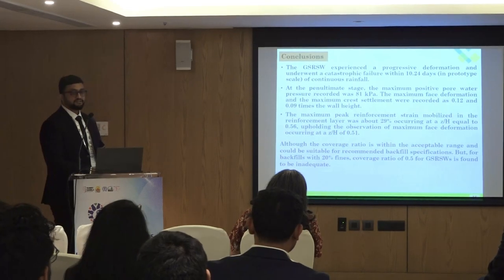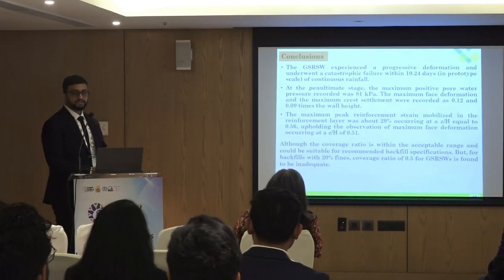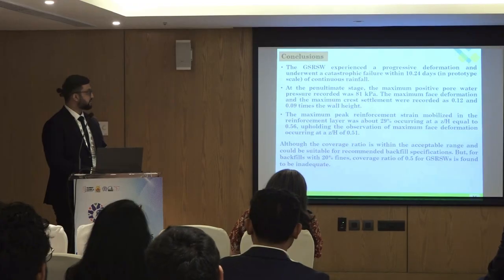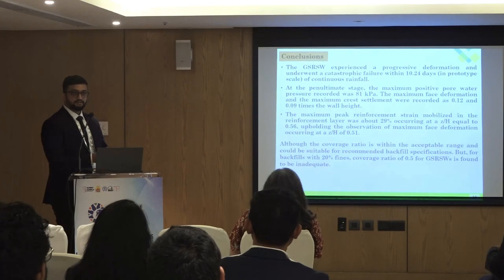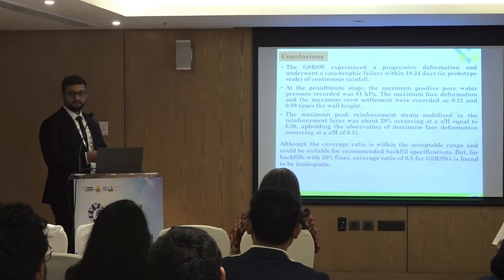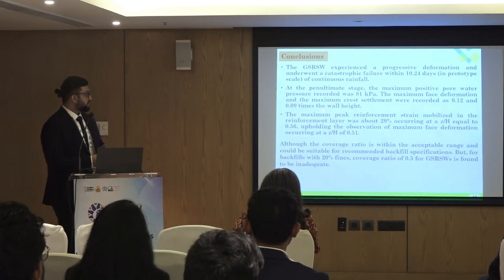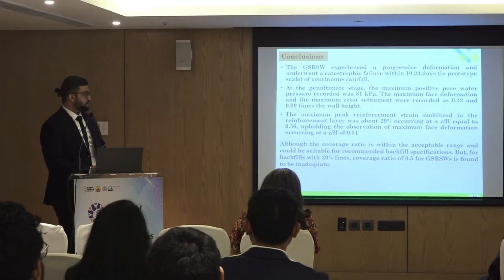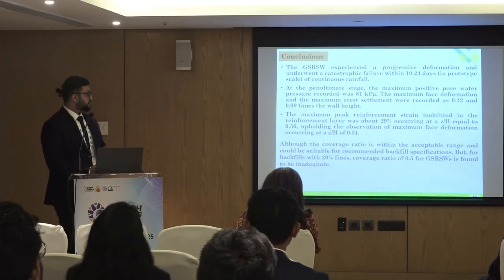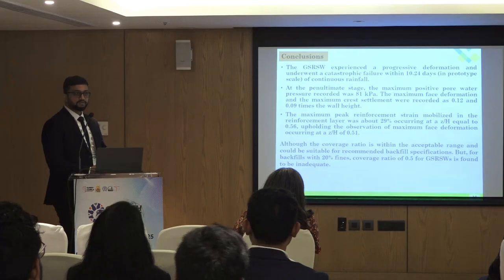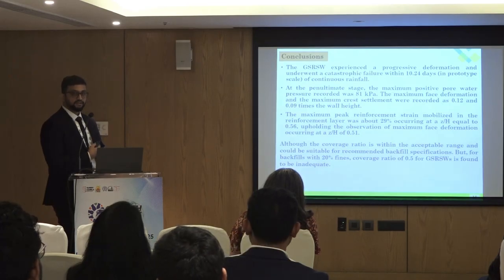Coming to the conclusions, the wall that we tested with a 0.5 coverage ratio failed at 10.24 days of rainfall. The coverage ratio that we usually select in the field starts around 0.45 and goes up to 0.7, 0.8. But the lower bound, 0.5, is not standing for a rainfall of 10 mm for more than 10 days. Maybe this 0.5 coverage ratio would be suitable for a fines content less than 15% or even less. When the fines content is increasing, a 0.5 coverage ratio would not be sufficient.